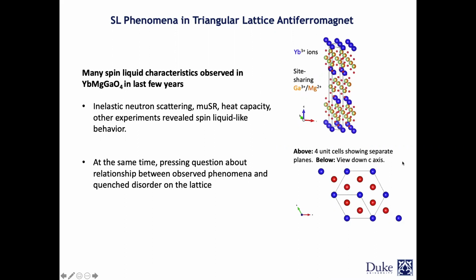So this is forming a triangle lattice. So practically you can see them here in blue. And then there is going to be a non-magnetic insulating layer between them, which is the gallium and magnesium. One thing that you should note is that this gallium and magnesium, as you can see here, they do have a site mixing, which means that practically it is impossible for somebody who is trying to synthesize this compound to say exactly where the gallium and magnesium should be sitting in this layer. It would be random. So it can introduce some things into play which are important, both positive and negative consequences. But let's just focus on the ytterbium ions, which are magnetic, and then let's see what is going on in here. So we are having a triangle lattice, as you can see in here, with the ytterbiums. So again, it goes back to what we talked about in Anderson's proposal.